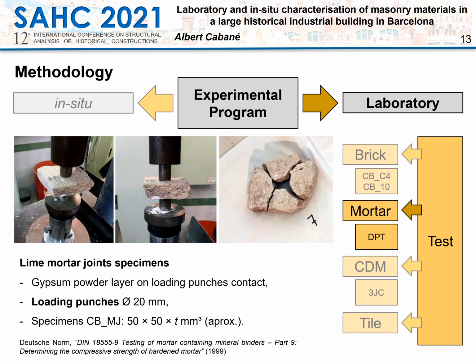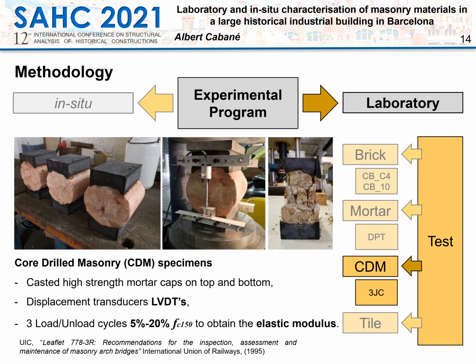However, given the large number of samples collected, the analyzed samples have sizes close to the standardized ones. To characterize the core-drilled masonry specimens, two high-strength mortar caps were cast on the top and bottom, creating two flat surfaces. The specimens were tested in two stages.